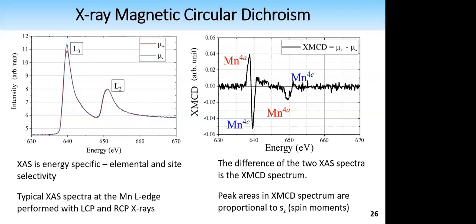So because I am interested in the sublattice moments, I assume that the areas of the two peaks in the XMCD spectrum shown here, so around the L3 region, so this first peak corresponds to manganese 4A, and the second peak corresponding here to manganese 4C. So I'm assuming their area is proportional to their spin moments. Now, this is in violation of the sum rules. And what I will get is that the spin moments will be in arbitrary units. And in order to normalize them, I will be using magnetometry data. So I'll be showing you how this can be done.